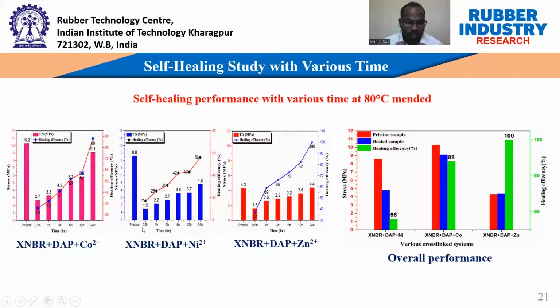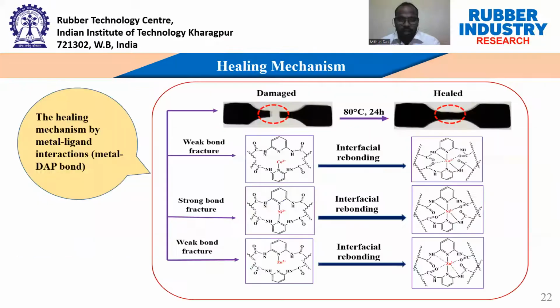So in case of this, this is the XNBR DAP plus cobalt system, this is the XNBR DAP plus nickel system, and this is the XNBR DAP plus zinc system. Finally, for the DAP plus nickel system at 80 degrees centigrade after 24 hours, the healing efficiency is 56%. In case of the cobalt system, the healing efficiency is 88%, and in case of the zinc system, the healing efficiency is 100%. So that means the zinc modified compound is completely healed at 80 degrees centigrade after 24 hours compared to the cobalt and nickel. And then we have understood the healing mechanism.